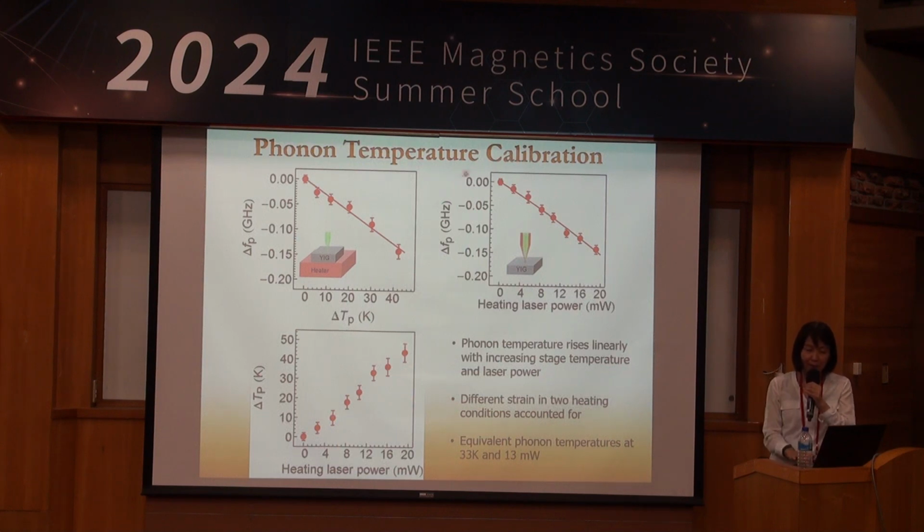Now, to understand things like spin caloritronics, I need to create a spatial non-equilibrium, but one that's also steady state. So what I then do is take a laser to heat up the sample locally. Now I expect a temperature profile. My laser beam is always a Gaussian beam, right? Then the middle heats up the most.